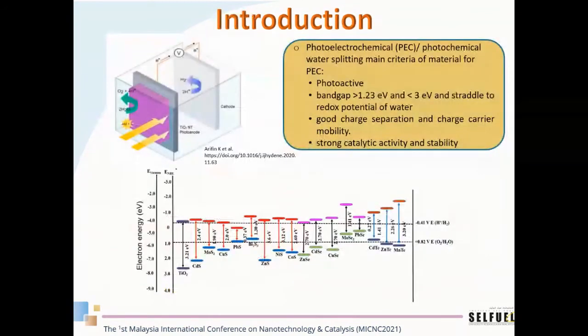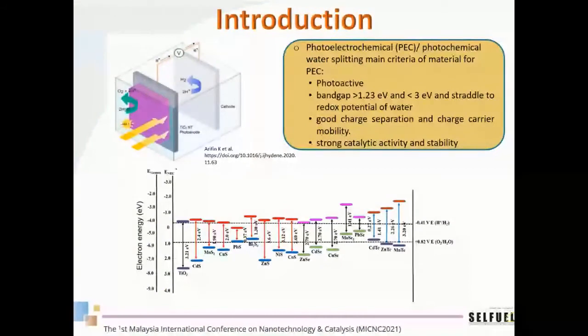There are several requirements for a material to become a photoelectrode. The material should be photoactive. And then the photoactive material should have a band gap bigger than 1.23 electron volt and less than 3 electron volt. 1.23 electron volt is actually the thermodynamic redox potential of water. Meanwhile, if the band gap is bigger than 3 electron volt, the efficiency of the system will be very low because the photoelectron needs high energy to work, and photo-generated electron and hole easily recombine. Besides the band gap, band edge position is also important.